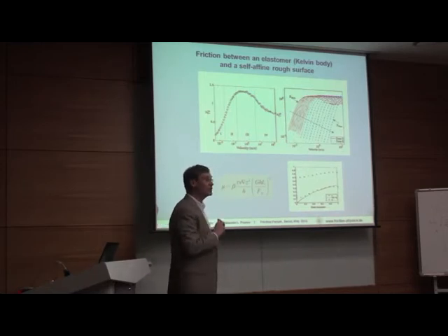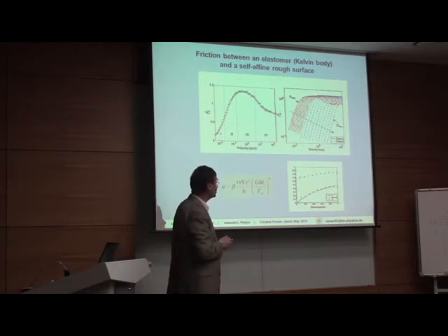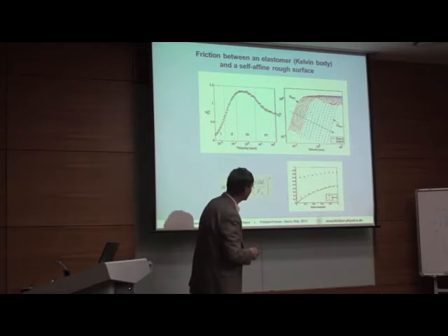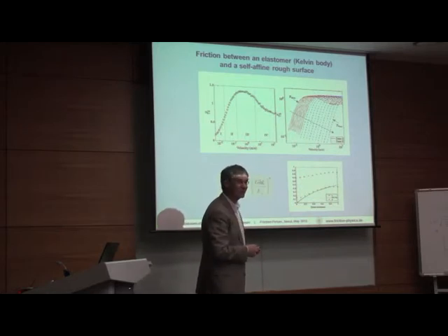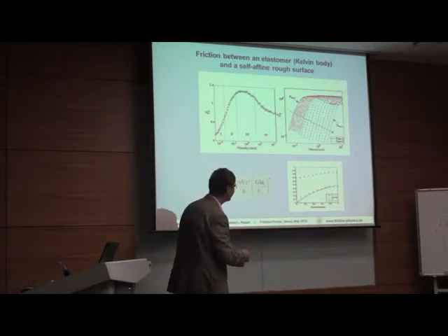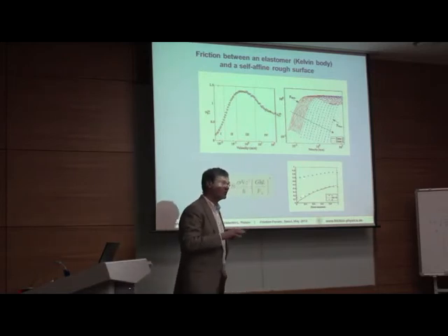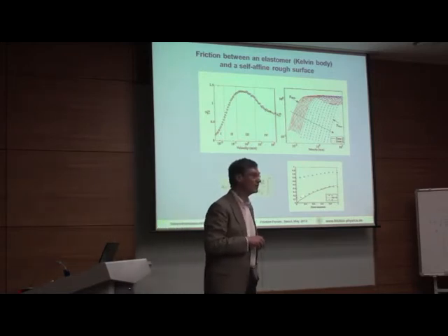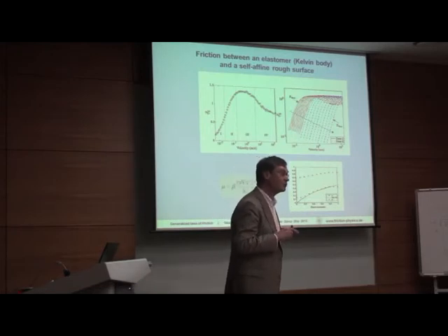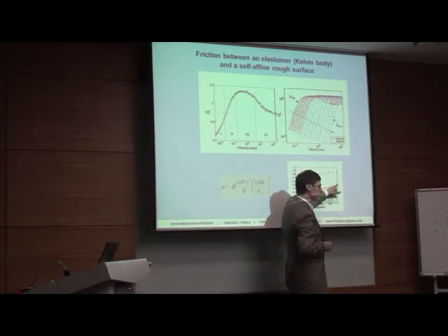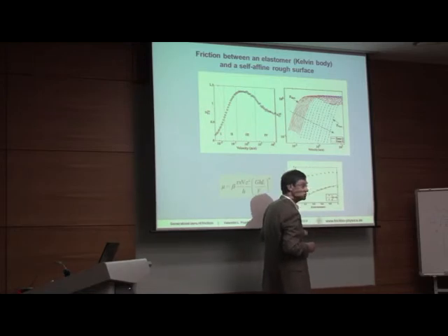These are results of alpha for different cases. It depends only on the Hurst exponent, and we also have a theoretical derivation, and this alpha must be H divided by 1 plus H. You cannot read it, but it is H divided by 1 plus H, and you see that it corresponds more or less to the empirical results. So it should be 1/2 at Hurst exponent 1, and it should be 0 at Hurst exponent 0.